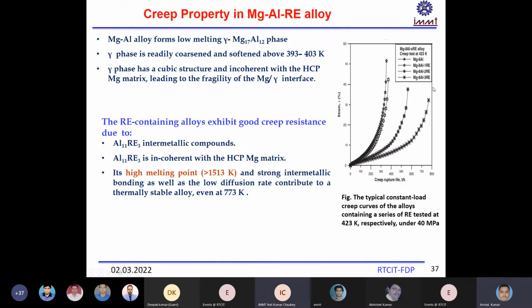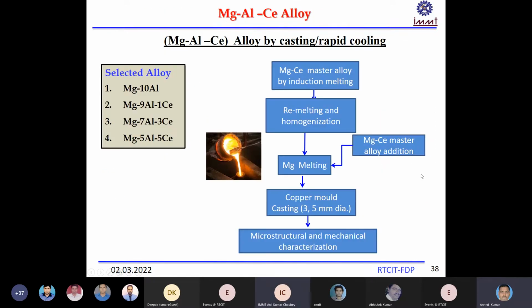Here you can see in this diagram, this is without rare earth, and then when you increase the rare earth element, your creep property increases. So here you can see at 300, 400 degree temperature, creep rupture strength is increasing. How did we make this alloy? In this schematic diagram, you can see we added cerium to the magnesium, cerium 1%, 3%, and 5%, to see the effect of the cerium.